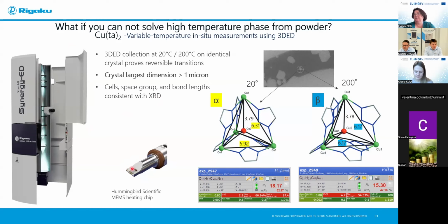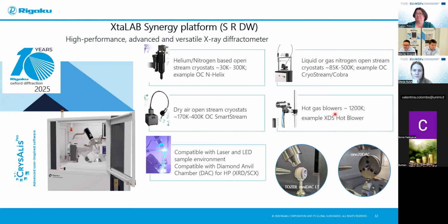an attachment or sample holder from Hummingbird Scientific with MEMS heating chips, which allows you to heat the sample in a similar range. And on the same grain or crystal, which is greater than 1 micron, you can get exactly the same structures. So if you cannot solve your crystal structure from powder after the phase transition, you can still go to Rigaku electron diffraction and, without recrystallization or changing anything in your powder, risking any changes, actually continue your measurements with Rigaku instruments.